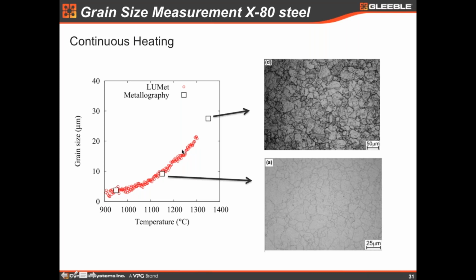Of course, this sample is different from this sample and is different from this sample because they have to be quenched and taken to the lab and get mounted, ground, polished, etched, go to the microscope and do quantitative metallography. So it's a lot of time consumed to perform this test. And with the LUMet, we have an excellent correlation with just one specimen. So in real time, we can just keep increasing the temperature and measuring the grain size. We can generate hundreds of points that might take weeks to do manually. So this is another application for recrystallization and grain growth for the LUMet.